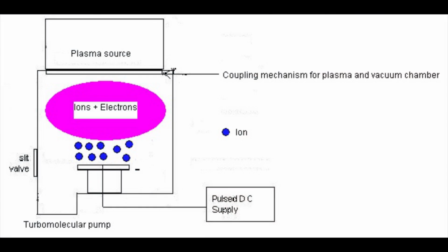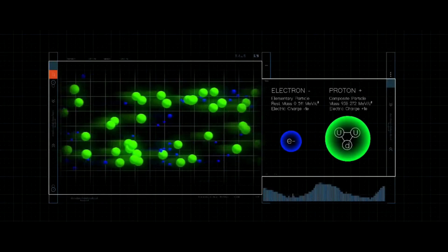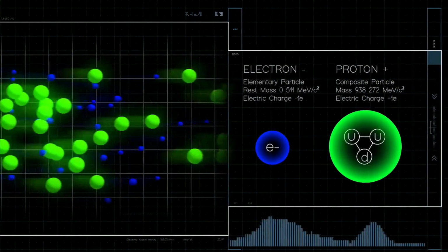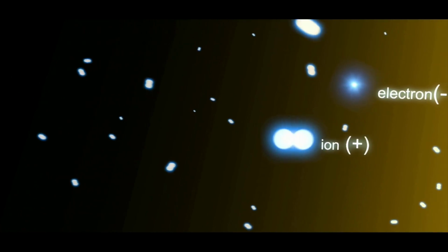Plasma source ion implantation uses high voltage filaments to ionize a gas in order to bombard and implant ions of the gas onto a material. Tungsten filaments were specifically chosen for this experiment because they approximate real solar wind by providing a lower energy bombardment. When an ion hits a material, there are several possibilities as to what will happen next. The ion can be reflected, it can knock off electrons, it can be implanted within the material, or it can cause sputtering. Sputtering happens when an ion makes a collision and then knocks off atoms from the material.